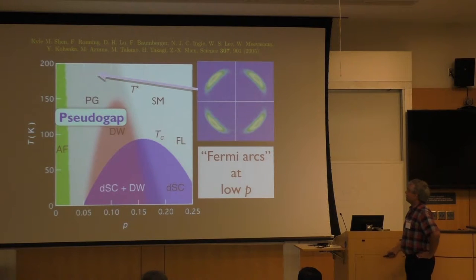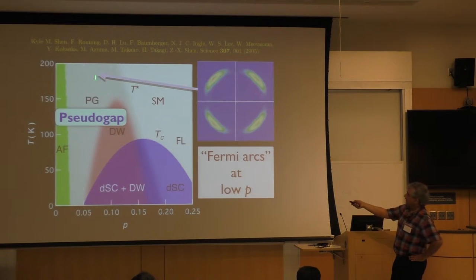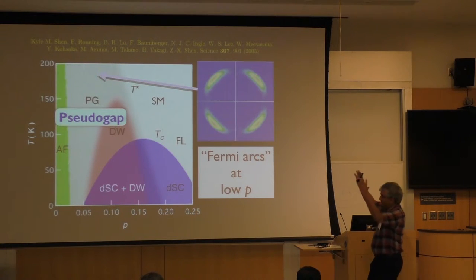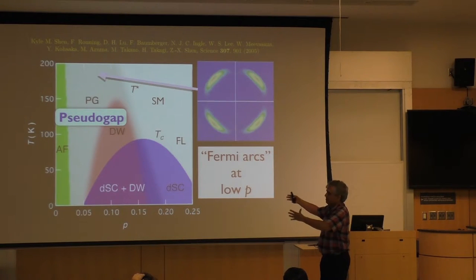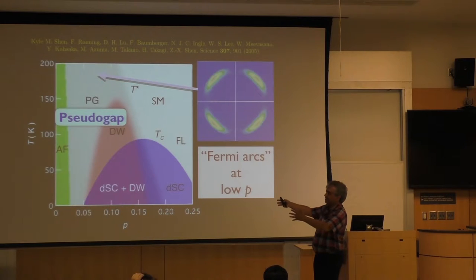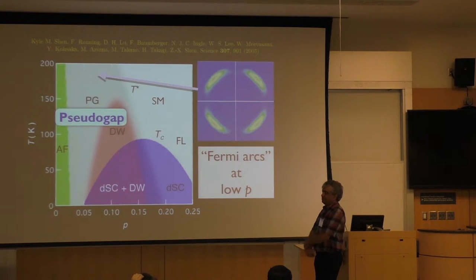All the indication from the experiments is it's actually something very simple. If you take fluctuating orders, as I said, that really has problems with the T squared behavior. I don't know how you get it — you have to start with a large Fermi surface and then reconstruct it, and that whole reconstruction depends upon the strength of your order, fluctuating superconducting or density wave. I don't see any reason why all these transport properties should depend on T squared.